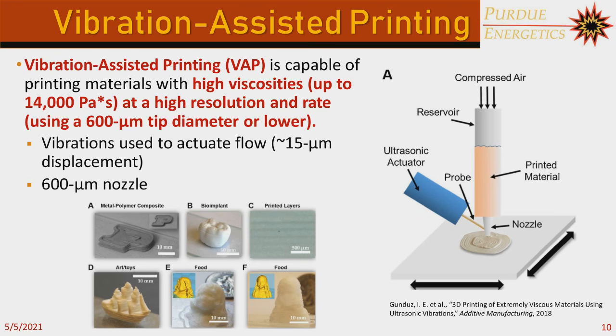The way that vibration-assisted printing works, essentially, is we have our custom material mixture put into a syringe, and then instead of just pressing it out with compressed air or a screw, we actually apply vibrations at the tip. If we didn't have vibrations at the tip, the material would just be sliding along these walls in the converging nozzle, and there'd be a lot of friction there. But when you apply these vibrations, the walls move relatively fast so that your material's not really experiencing the friction there, and it can just slide out rather quickly.